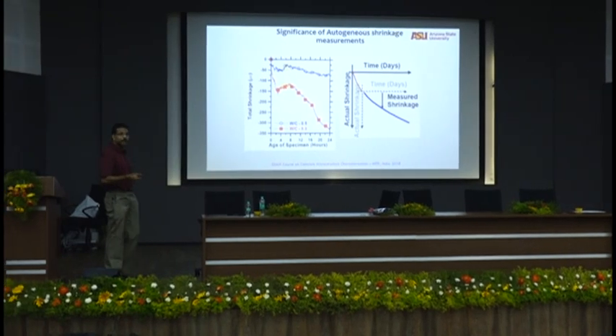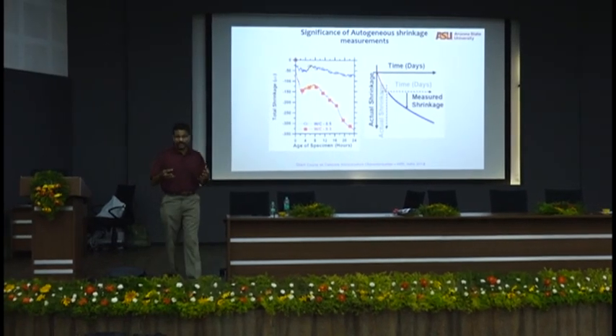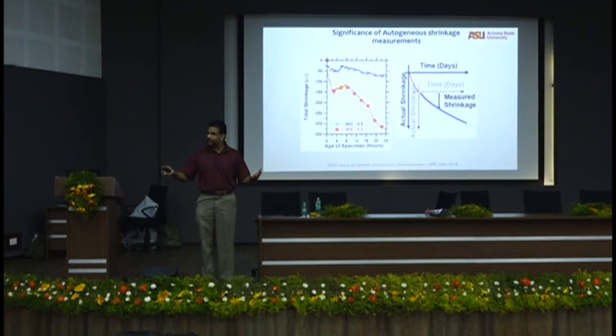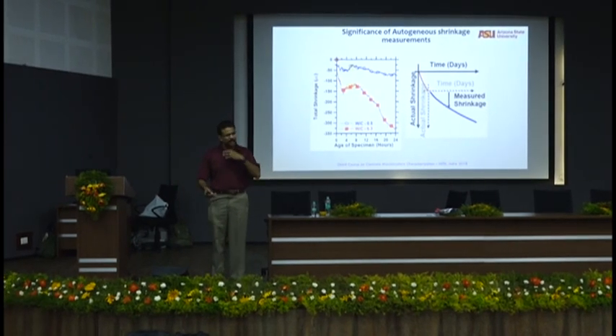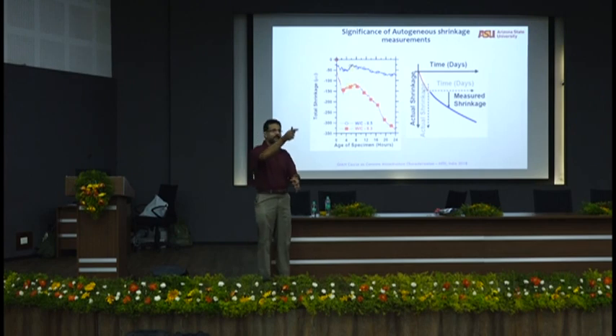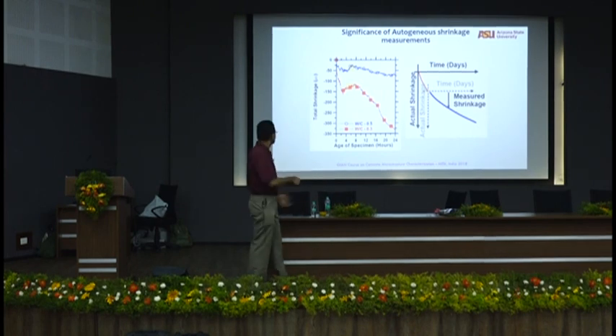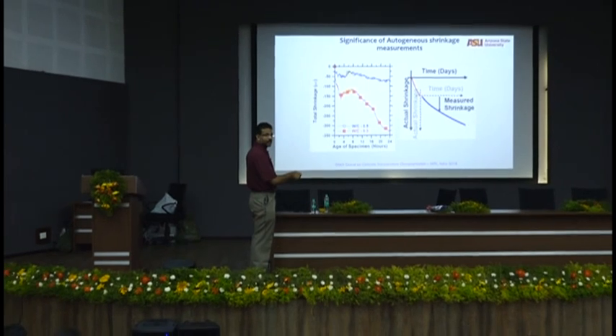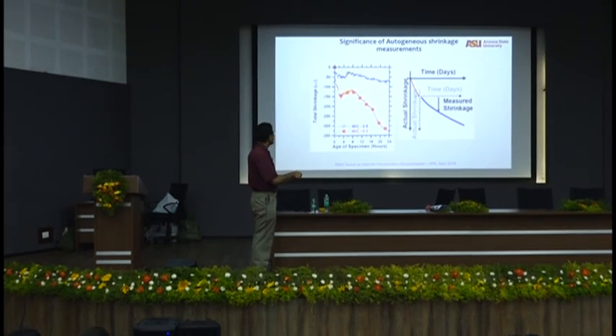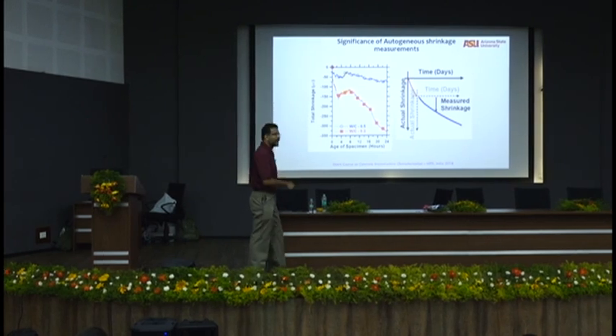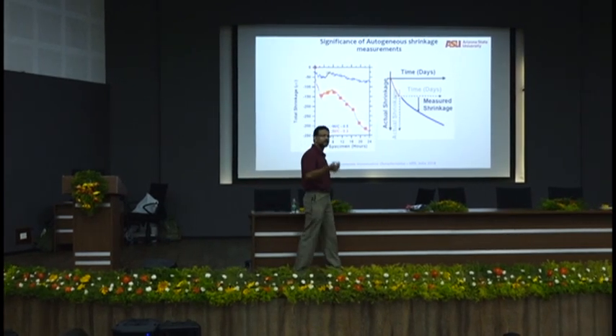So the other advantage with your ring test is that the residual stress that you measure in a ring test includes autogenous, chemical, everything, because you start measuring as soon as you pour your concrete. But if you're doing restrained shrinkage or a free shrinkage bar, when do you start measuring it? After 24 hours, which means you completely lose that part. You completely lose that shrinkage, and you're getting only your measured shrinkage, and then you're basing everything off of that, and people put in these random numbers.